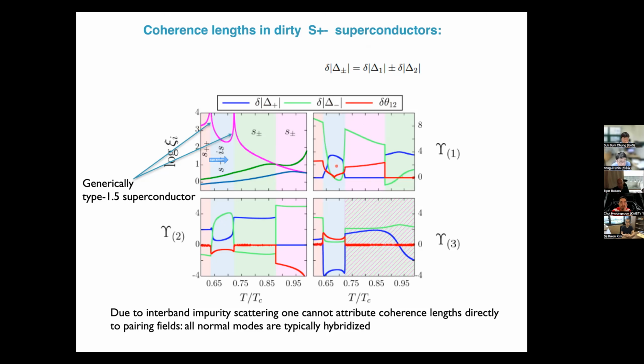And then the masses of this mode diverge near the symmetry breaking phase transition, and that you can see in principle through measurement of the Leggett mode as it is usually measured. That will show softening of the Leggett mode, but it also directly implies that vortex cores blow up. So the softening of the Leggett mode translates to divergent coherence length. Softening of the normal mode, if it is a Leggett mode mixed with amplitude modes, directly translates to breakdown of the type 1, type 2 dichotomy. Okay, thank you very much.